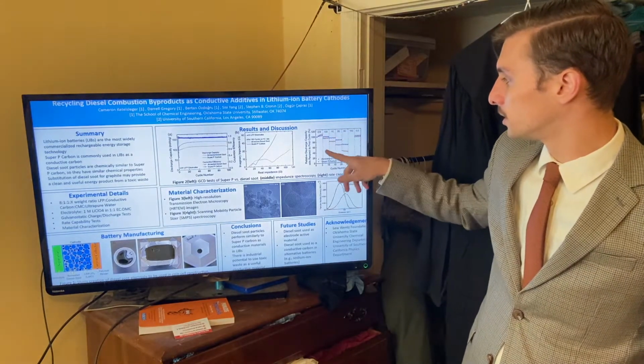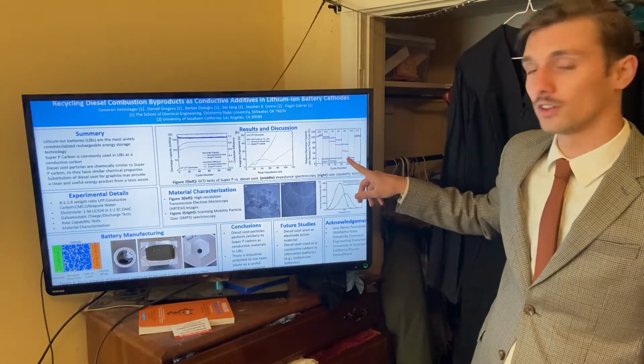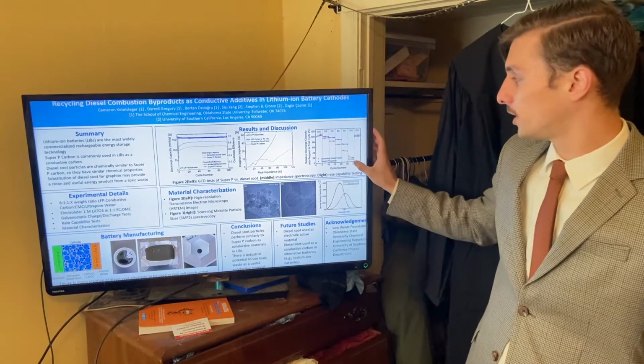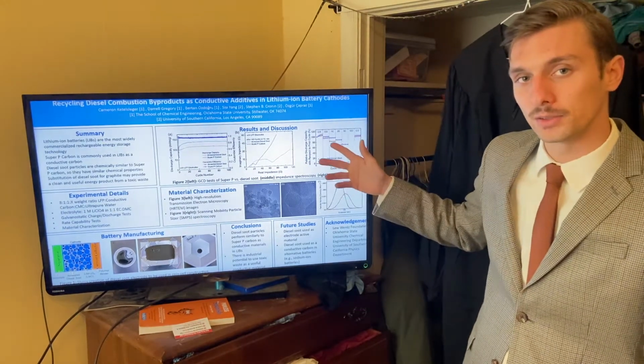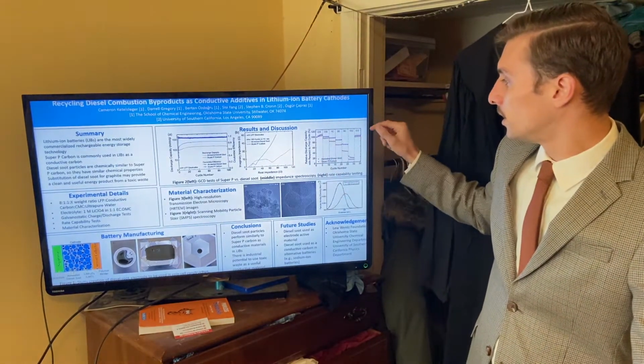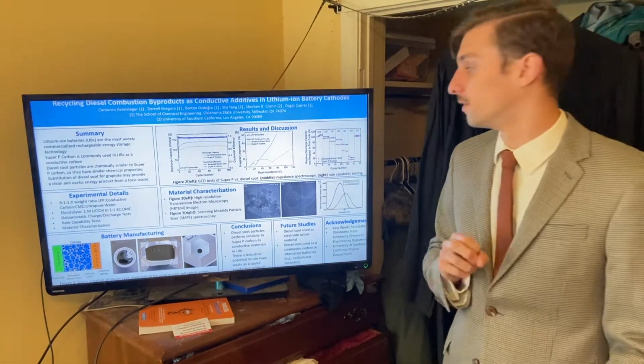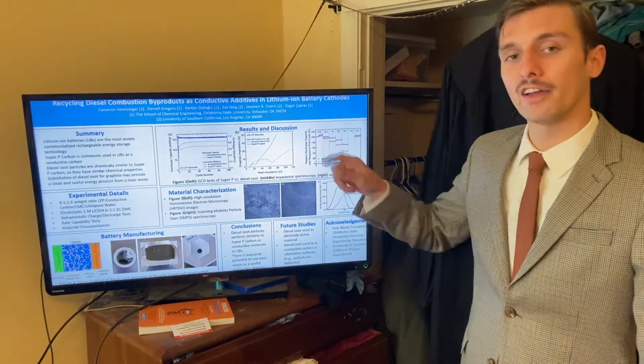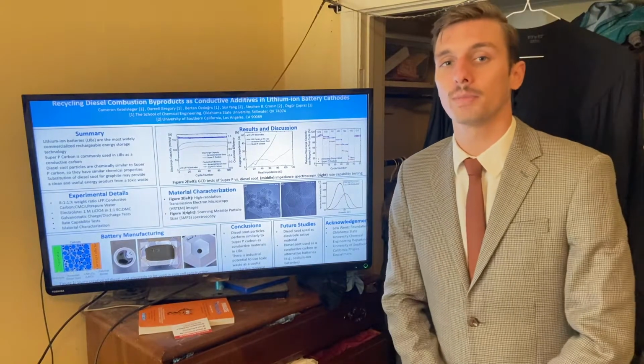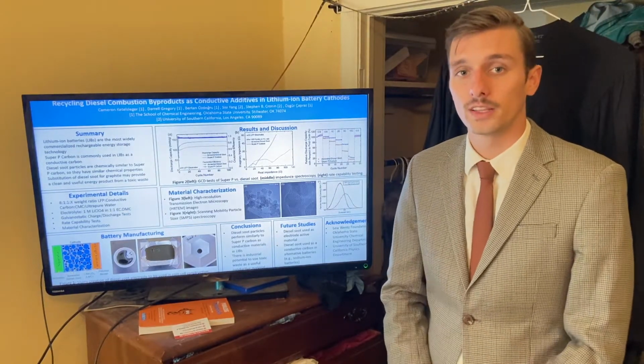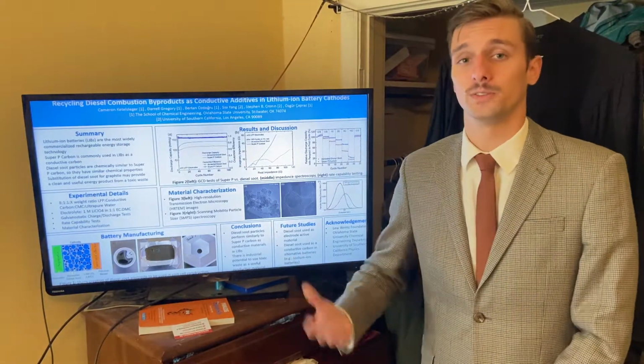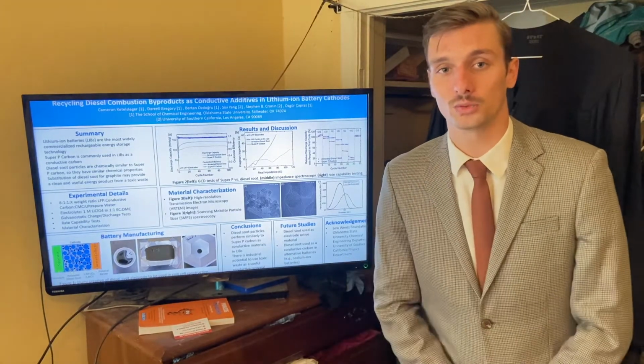Throughout all this, as you can see, there are some disparities along the way, but ultimately after 30 cycles of many different cycles, we see that a C/2, 2-hour charge rate provides 95% of the original capacity for both of the materials. That means that these are flexible materials. They can handle various charge and discharge rates.